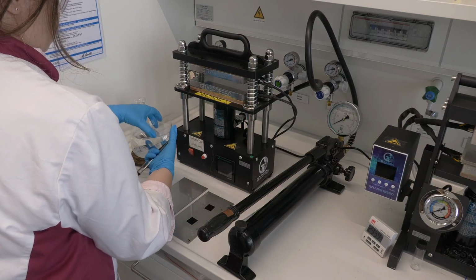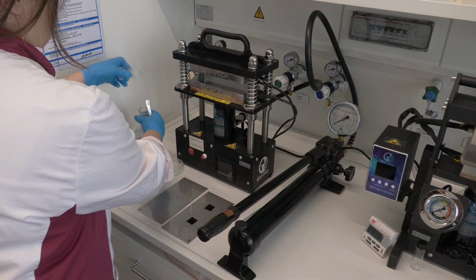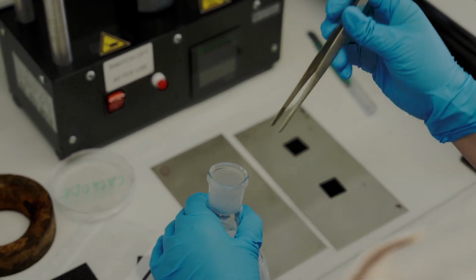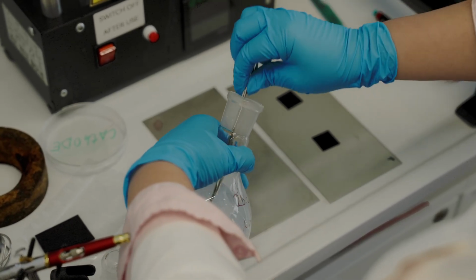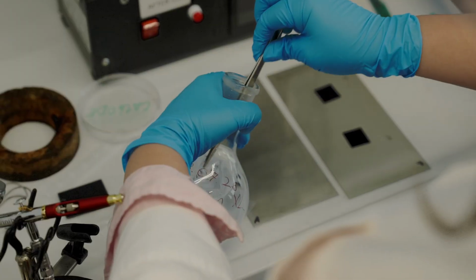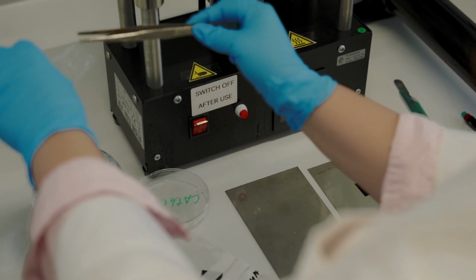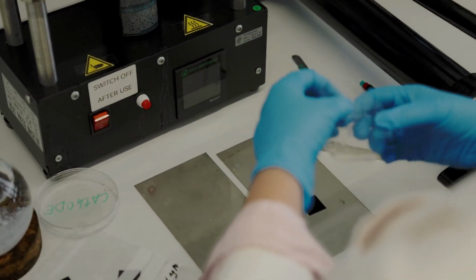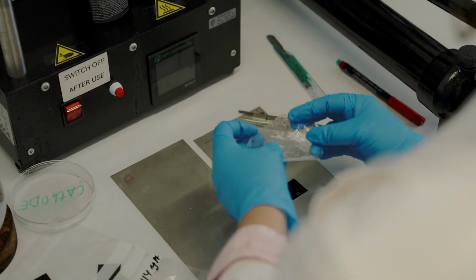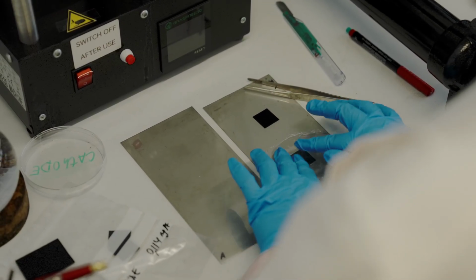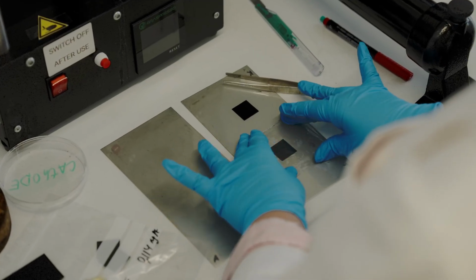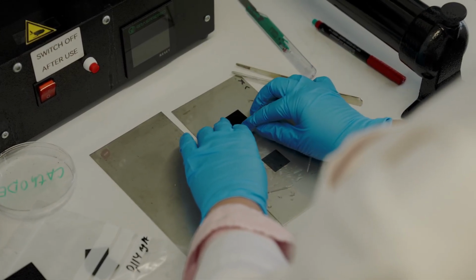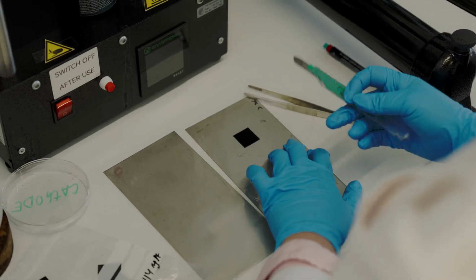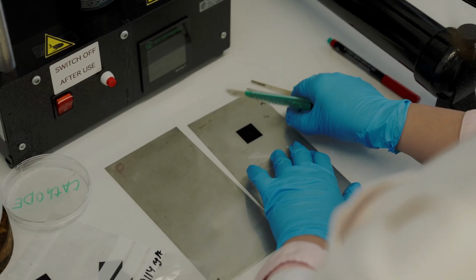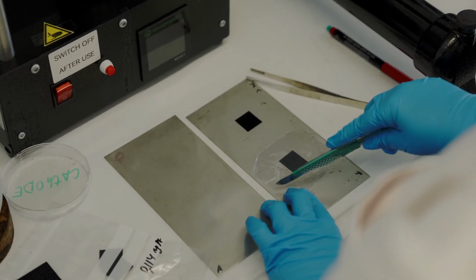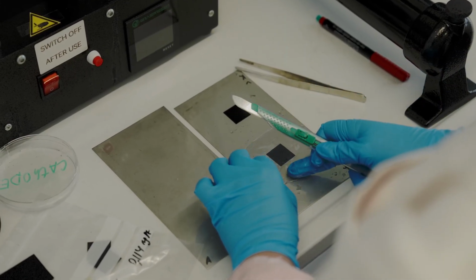Place the membrane on top of the cathode. It has been pre-activated and stored in deionized water. We cut off any membrane that folds over. This prevents unevenness during the pressing procedure, which can occur if several layers of membrane exceed the thickness of the layer.